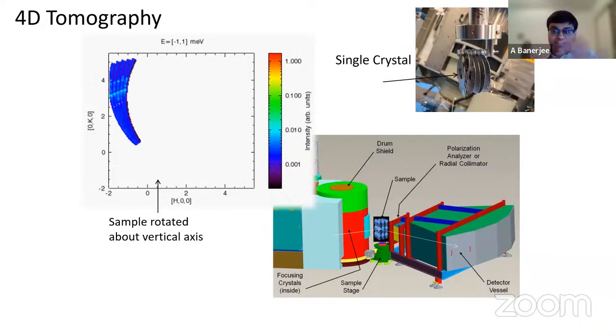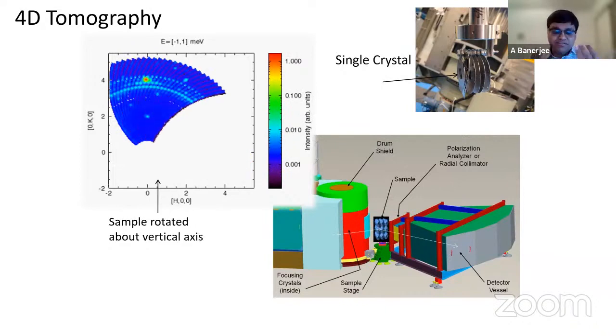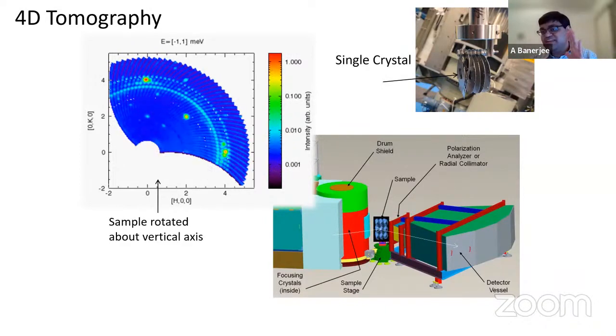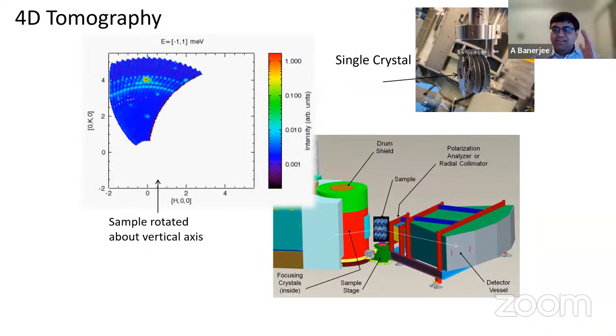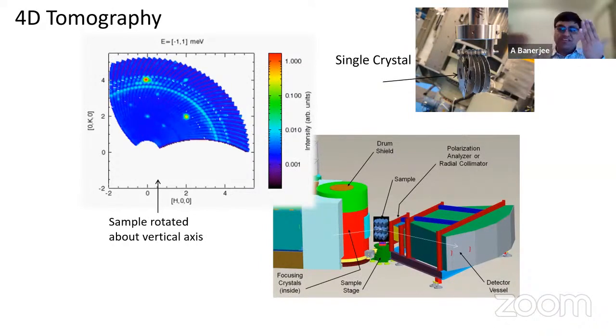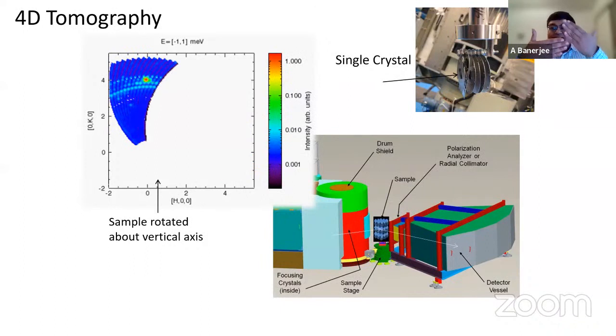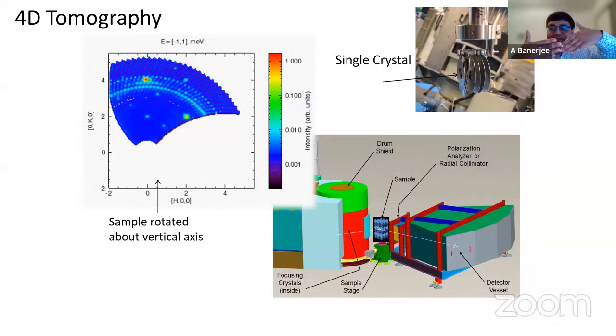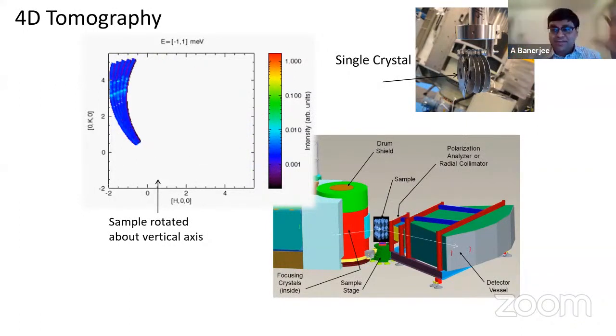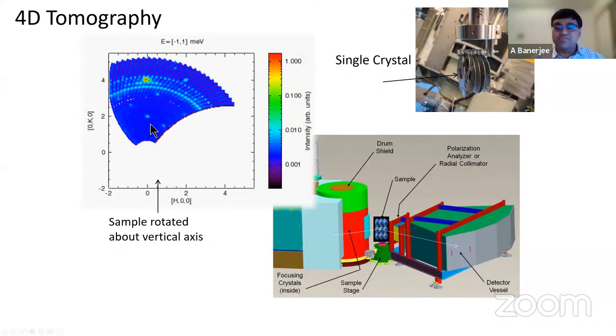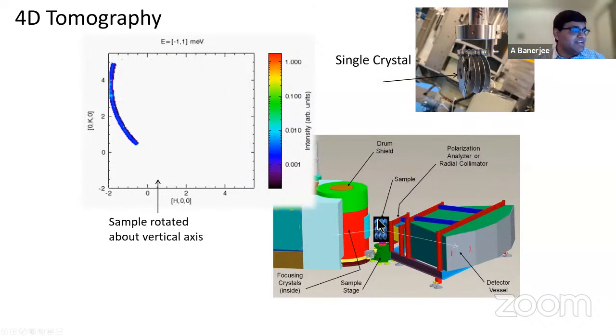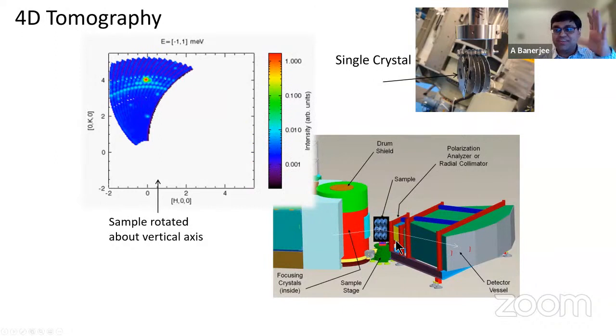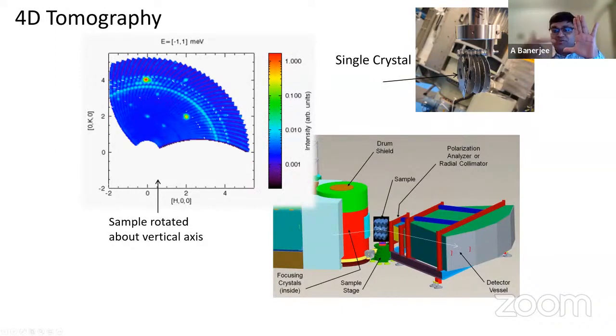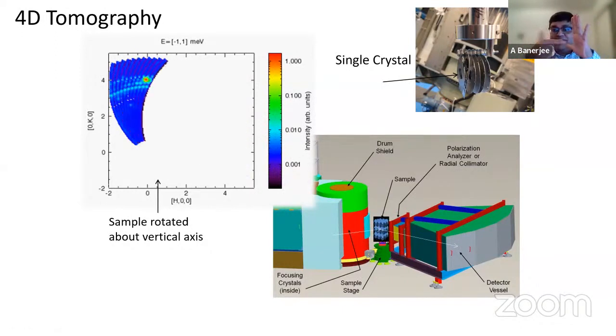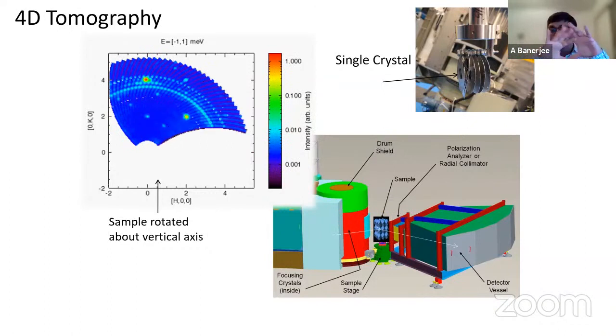Your sample is 3D, you need the 3D information, but in order to get it, you do exactly what you do in a tomography. Like in a tomography, you impinge your sample with a beam, and then you slowly rotate your sample, and then you construct your entire 3D picture. That is exactly what we do here. We keep on rotating our sample as the neutron hits, slowly rotate it, take a frame, slowly rotate it, take another frame, and then